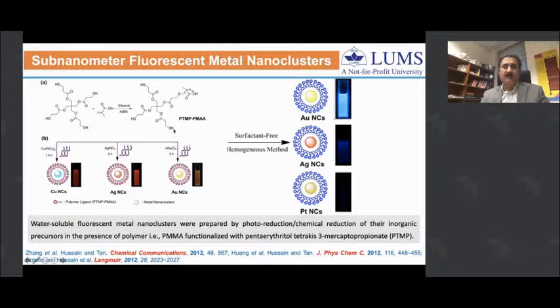Using these type of polymers, we were able to make copper nanoparticles, silver, gold, and even platinum and other metal nanoparticles which were smaller than 2 nanometers.